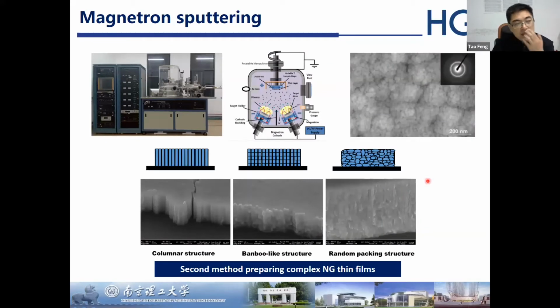The second way to prepare nanoglass thin films is the magnetron sputtering technique. By controlling the gas pressure, the power, and also the deposition mode, we can prepare different nanostructured amorphous films, like columnar structure, bamboo-like structure, or random packing structure nanoglass.